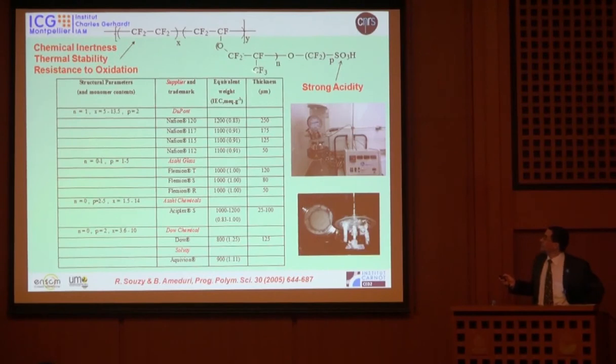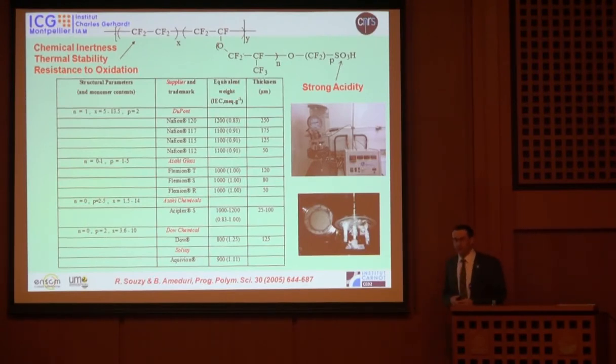This is a ring opening polymerization of hexafluoropropylene oxide from a sultone. I don't go in details, but again, organic chemistry is important. And usually this monomer contains a sulfonyl fluoride group, which is hydrolyzed later on after making the copolymer into sulfonic acid.